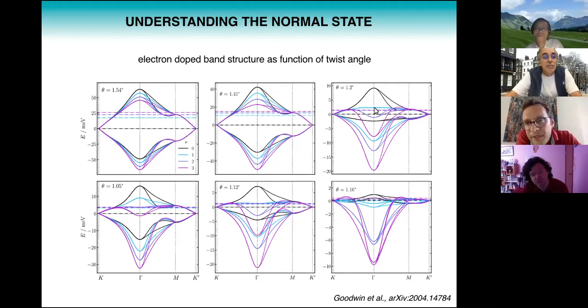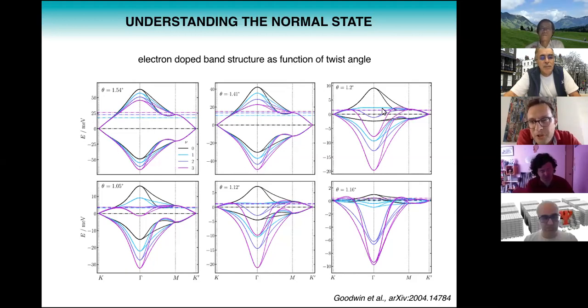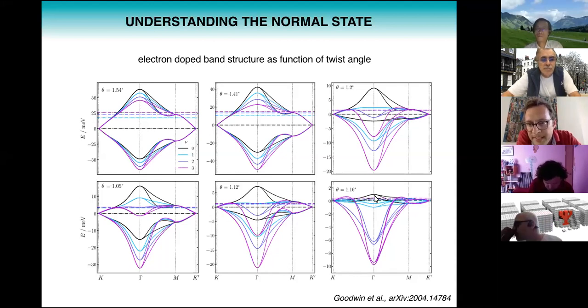The bands have gone very flat for nu equals 1, but then for nu equals 2, the conduction band has actually completely inverted. Right? So you get qualitative changes, not only deformations and distortions, but actually qualitative changes to the band structure. And the interesting thing is you get these extremely flat regions in the bands near gamma, right? So basically completely flat bands. And then if we look at 1.16, which is very close to the magic angle in our method, you see the neutral band structure is basically very flat.